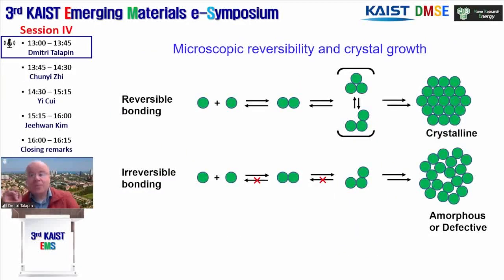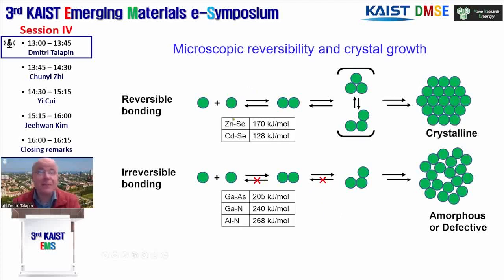So the real problem, if we think deep into why we cannot grow some materials by solution chemistry, comes not from our inability of making chemical bonds, such as the gallium arsenic bond in solution, or the gallium nitrogen bond, but actually the opposite, from the inability to break these bonds. Because for growing crystals, especially in 2D and 3D cases, the chemical bonding must be reversible. We need to be able to repair occasional misbound fragments in order to grow crystalline material. And if we don't have reversibility, we will run into a problem. And that can be demonstrated with an example.